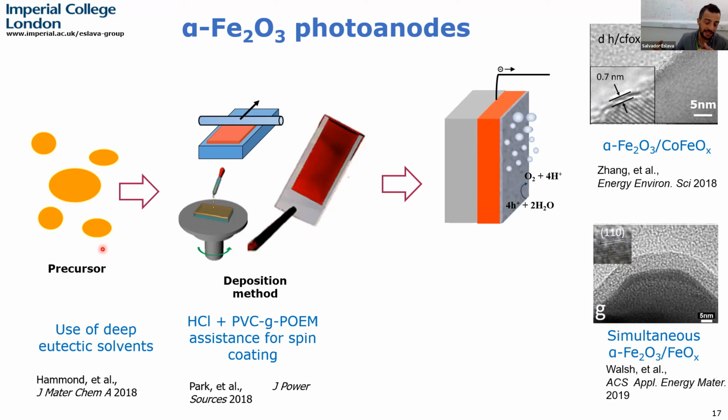So we found this way a greener way to prepare the iron particles, because also the deep eutectic solvent is greener itself, is prepared with choline chloride, which is a food additive, and urea, which is a fertilizer. So it's cheap and non-toxic, and it allows us to use iron nitrate. And we obtained good photoanodes, similar to the ones prepared with an iron pentacarbonyl toxic source.